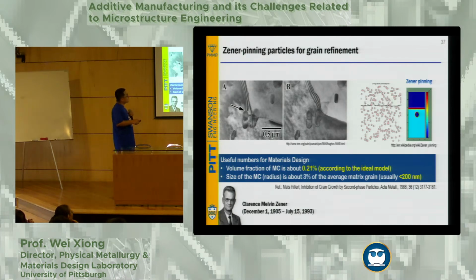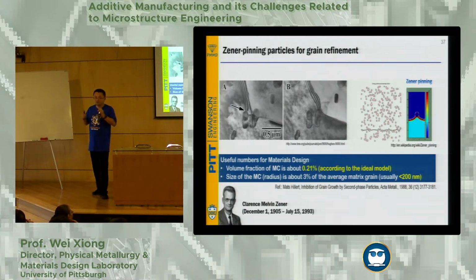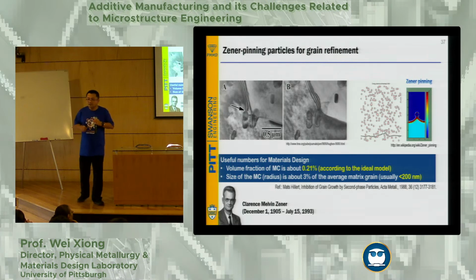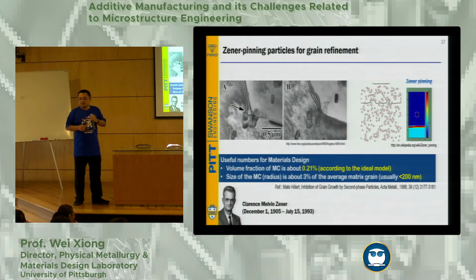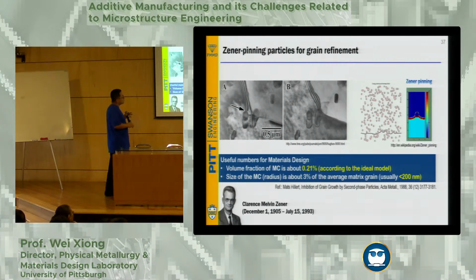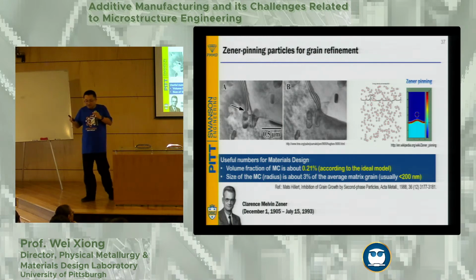For the Zener pinning particle - basically this is from Wikipedia, I don't think it's a real picture, but it gives you the concept - if some of the particles, for example in steel the MC carbide particles, are small enough, say less than 50 nanometers, then you can have a pinning effect once the grain boundary crosses this Zener pinning particle. This can delay grain growth and ensure you get a fine grain.